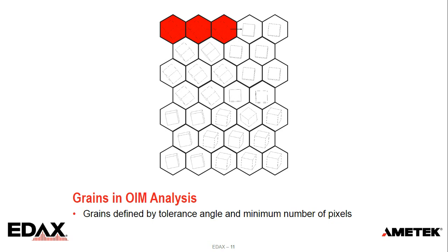And I just want to point out here, our default tolerance angle is 5 degrees. So if the misorientation between the first and second pixel is, we'll say, 4 degrees to keep it round, and the misorientation between the second and third pixel is 4 degrees, the misorientation between the first and third is then, of course, 8 degrees. So you can get a lot of grain orientation spread within a particular grain, even if the misorientations between points are lower. And we'll see some examples of that a little bit later.